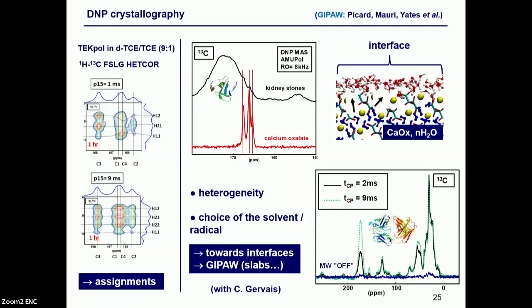And from a chemical point of view, and I'm interested in this currently, you can choose the DNP juice in order to check the heterogeneity of the samples. They are heterogeneous, and by playing with the DNP juice, you can enhance the role of one component, for instance here the protein part, and you can completely underestimate the role of the oxalate. So if you want to completely understand and explain these spectra, then you have to go again to a description of the interfaces. So you have to model them and do the GIPAW calculations.